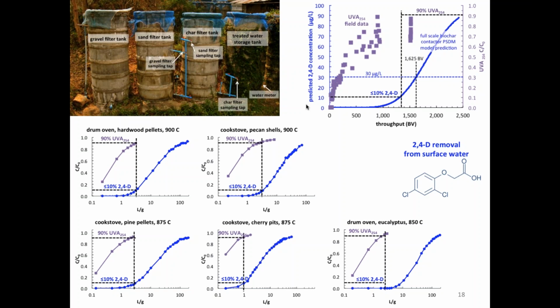I don't want to give you the impression that the formula is always 90% UVA breakthrough to 10% 2,4-D breakthrough. It's not that hard and fast. We're looking for field feasible measurements that can give us conservative indicators of how well the systems are performing. This UVA is one approach that's a work in progress. So it's nice to see a reasonable degree of field confirmation for something that we developed in the lab. That's mainly the take-home point. Don't get too attached to the specific numbers of 90 and 10.